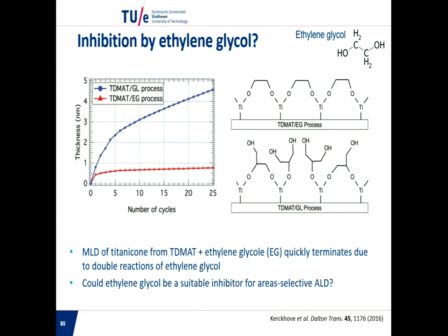But it's not reacted there forever. It still can be flexible and react with the ligand that you're going to use for the deposition. Yeah, there is a probability that it will react with ethylene glycol, because those bonds are not fixed forever. So I think it might be a bit of a dynamic system. The other thing is that of course this only works if all of them react like this. So if a fraction reacts in the monodentate configuration with the reactive group pointing up, then of course that's a site where your precursor can adsorb. So then you're lost and you lose your selectivity.